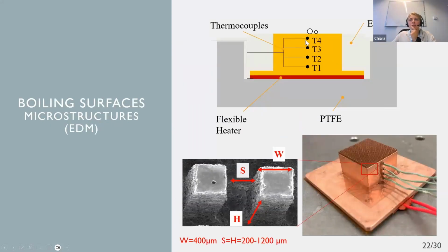The test section, you can see the schematic on top and a picture on the bottom, was made in copper with traditional machining. The boiling surface is 20 millimeters times 20 millimeters, and we installed 4 thermocouples along the vertical direction to measure the temperature of the copper and evaluate the heat flux going through our boiling surfaces. The copper is heated by flexible heaters that were simply mounted on the bottom side.